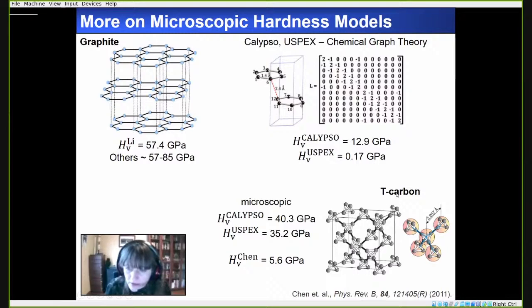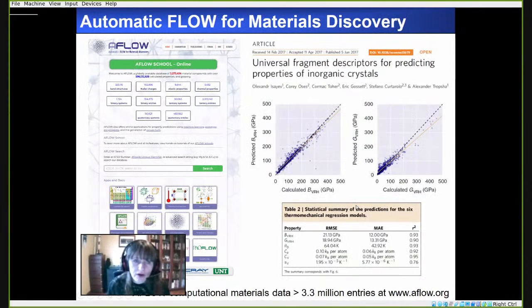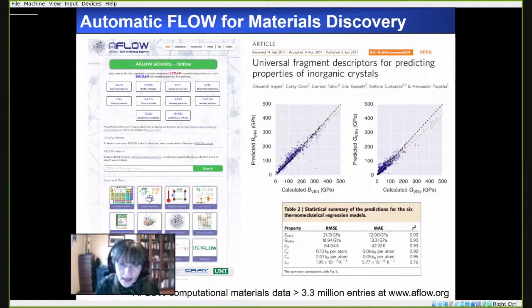For example, we have this T-carbon allotrope, which is a hypothetical allotrope. It is very porous. And even though each carbon atom is tetrahedrally coordinated, you would not expect them to be very hard. So the Calypso and Uspex still give a reasonably high hardness, whereas the macroscopic hardness models give a much lower hardness prediction.